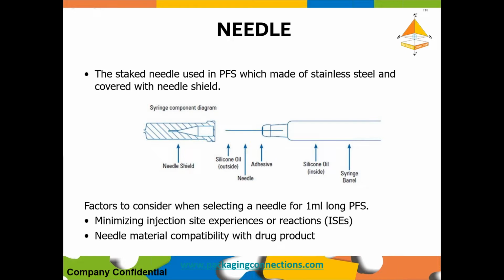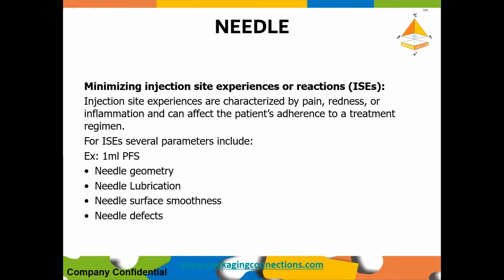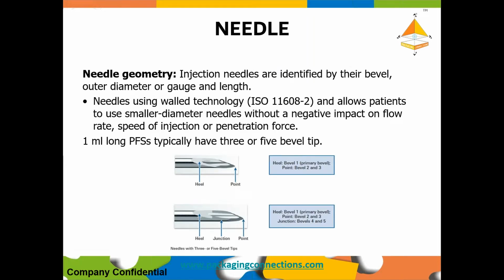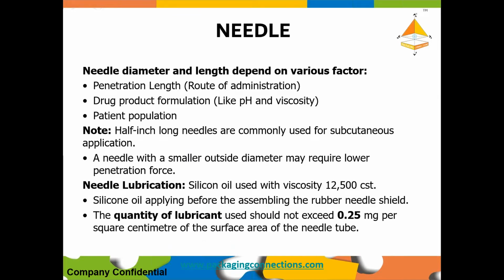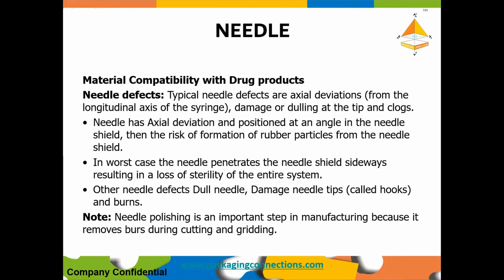Staked needle, then this is covered with the needle shield. In this case, minimizing injection site experiences or reactions. Needle material has to be compatible with the drug product. Very important parts for the needle: geometry, lubrication, surface smoothness, needle defects. The needle geometry is an important part so that it does not hurt. Different diameters based on the different penetration length and so many different things. Needle defects.